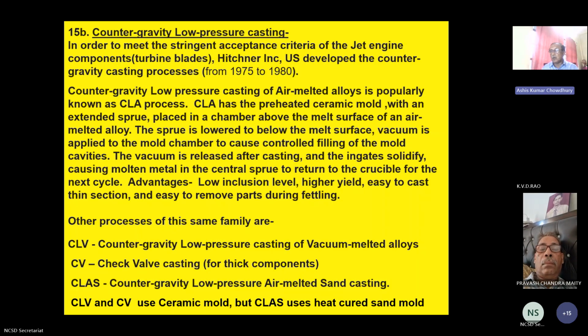Advantages of this one are low inclusion level, higher yield, easy to cast thin sections, and easy to remove parts from the gating during fettling. Another process is CLV, counter gravity low pressure casting of vacuum melted alloys. Here the melting should be done in vacuum. Then there is the check valve system, CV system, for thick components. CLAS is counter gravity low pressure air melted sand casting. CLV and CV use a ceramic mold, but CLAS uses a heat cured sand mold system.